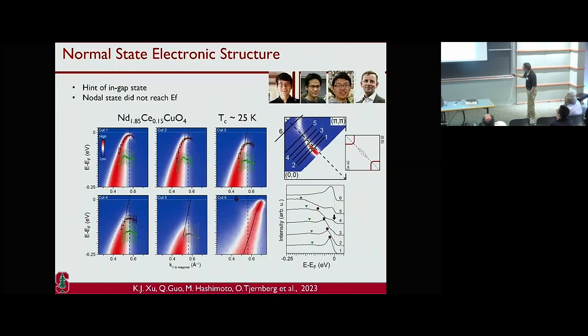You can see cut 1, 2, 3, and 4, 5, and you see cut 1 is around node. Well, this sample has a TC of about 25 Kelvin, and you can see this band sort of bends back. It did not quite reach the Fermi level. That means the nodal piece is more like a dashed line. On the other hand, look at cut number 6 here. The antinodal piece is very clear. Okay, it reaches the Fermi level.